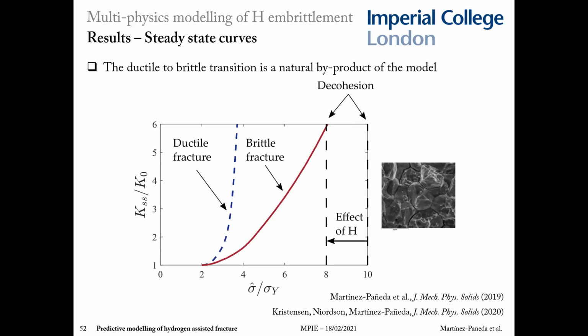So you can find more details of this rationale in the papers, but the key thing that I want to emphasize is that the model can naturally capture the change from a ductile fracture prediction to a brittle one once hydrogen reaches the fracture process zone. Or in other words, the combination of strain gradient plasticity, interface strength degradation due to hydrogen, and a fracture process zone model provides a modern rationale for the so-called hydrogen enhanced decohesion mechanism, in my opinion.